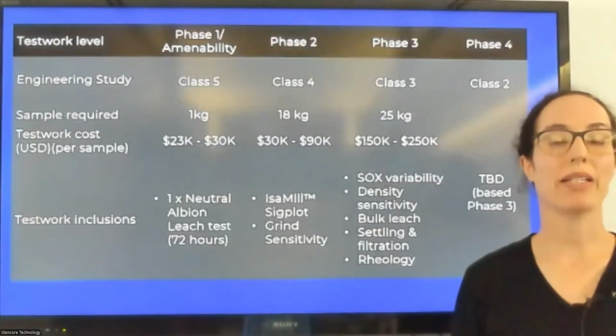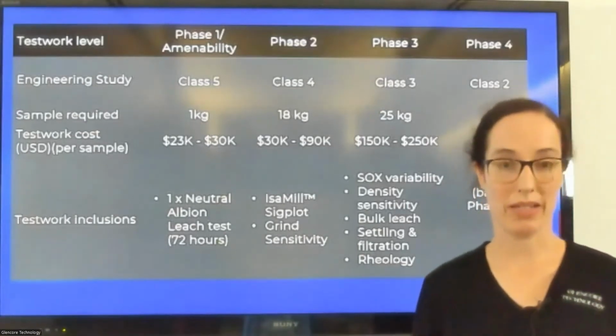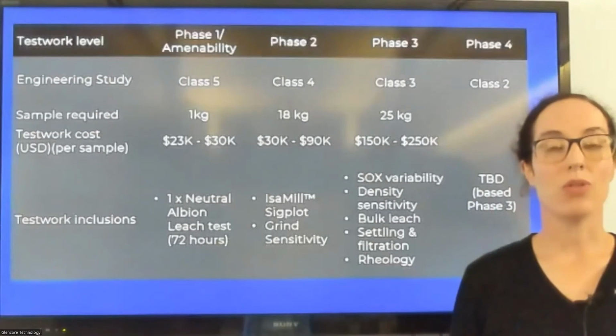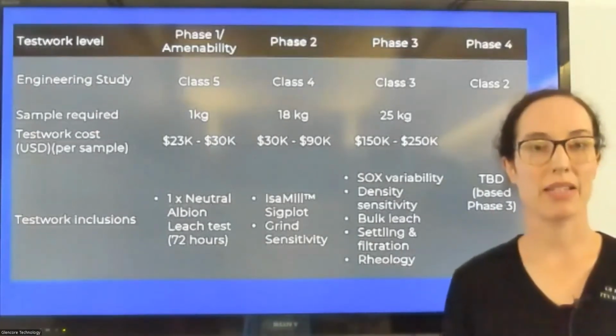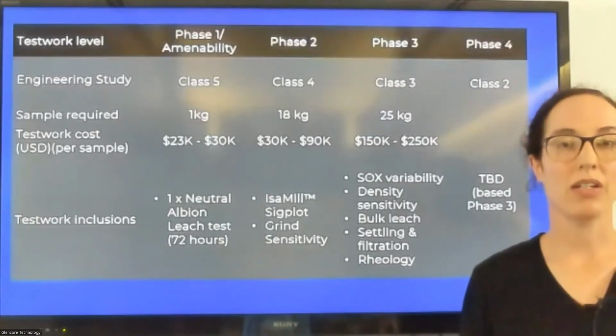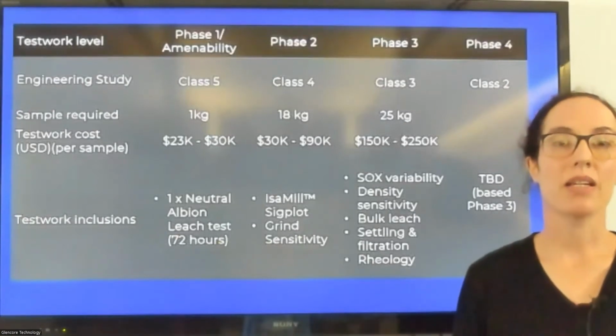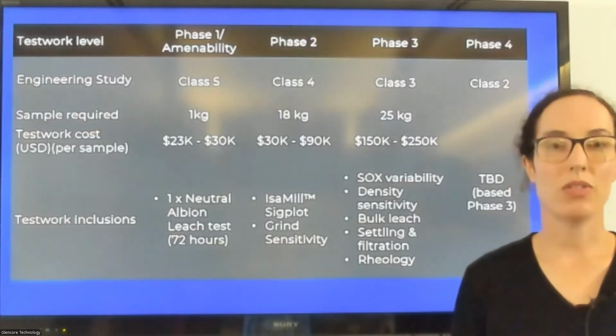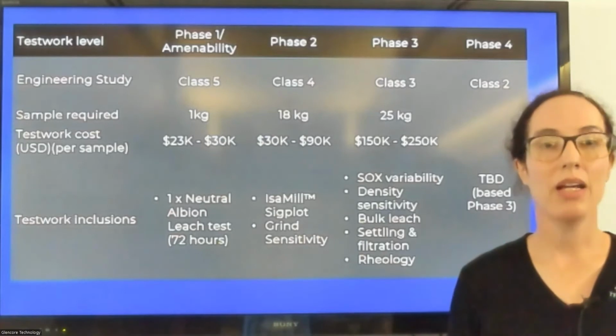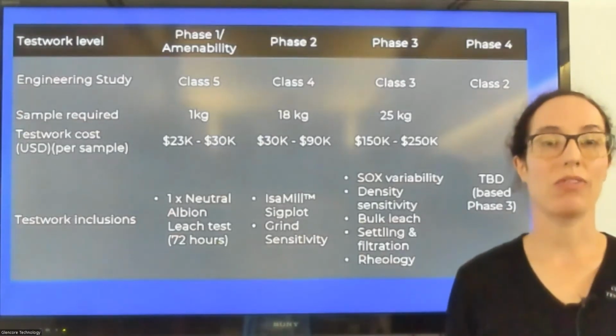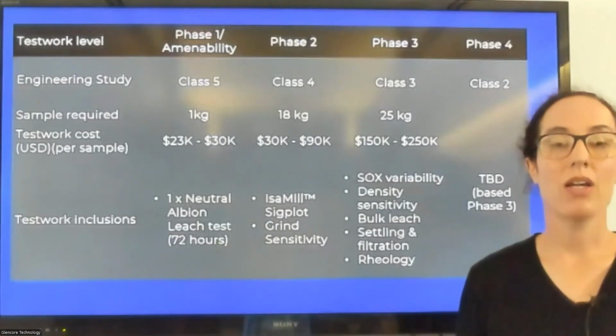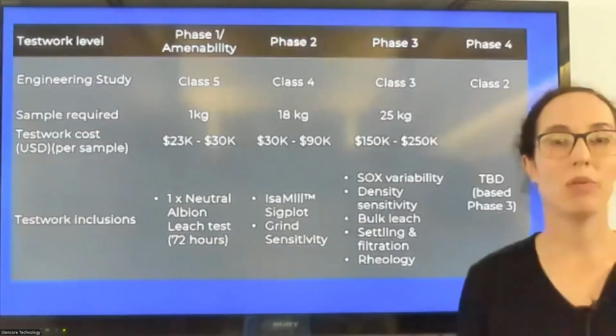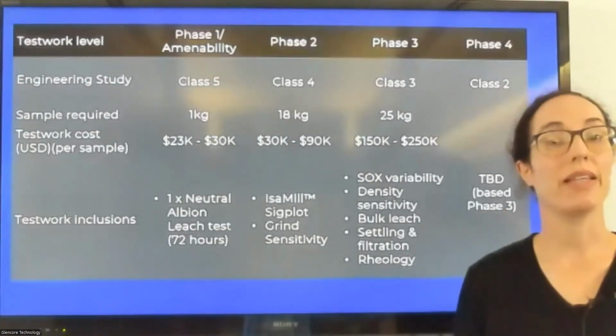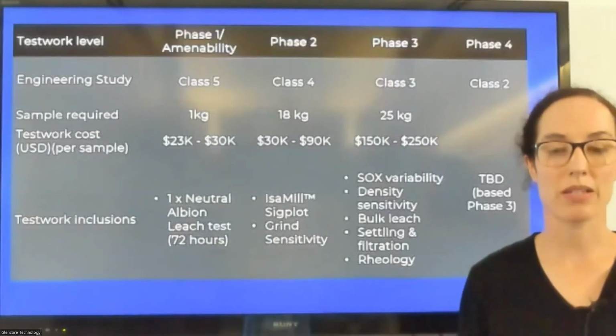Here, we are looking more at the practicalities of the leaching portion of the Albion process. To this end, we do 3 so-called SOX variability tests. By SOX, I mean sulfide oxidation. In that initial amenability test, the extent of sulfide oxidation after 72 hours would have been probably more than 80%. And normally, you don't actually need 80% of sulfide oxidation to open up that sulfide matrix. So in this phase, we are looking at different residence times with therefore different sulfide oxidation extents to work out what the minimum is that will still give you good gold recovery in the CIL subsequent to the Albion process.